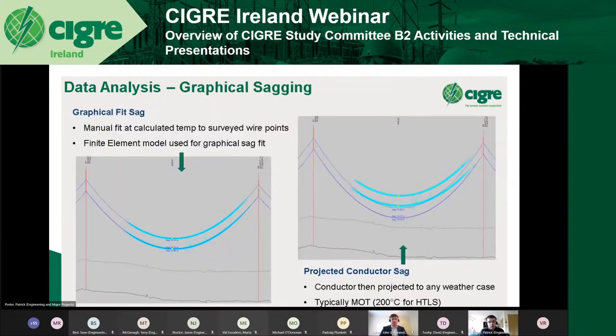So after we've calculated the conductor temperatures, the final step is to combine those calculated conductor temperatures in PLS-CADD with the point cloud data collected from the laser scanner. You're just looking at a 2D profile there through span 57, 58 with your point cloud data loaded in from your laser scanner, and your calculated conductor temperature, in this case 103 degrees Celsius. So simply what we do is it's known as a graphical SAG function in PLS-CADD using a finite element sag tension model.